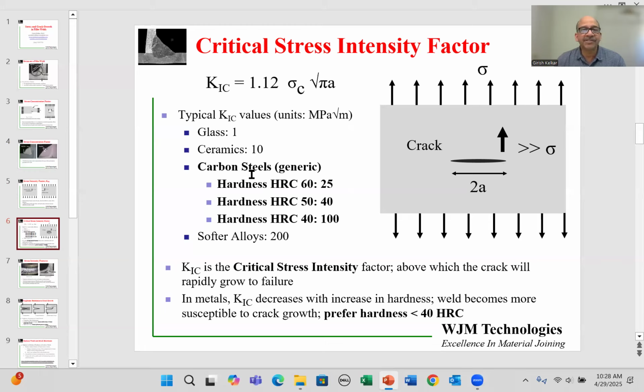Further down, carbon steels, which is our favorite material for welding most of the time: when the hardness of carbon steel is 60, which is very, very brittle, almost like a rock, the K1C value is 25. So anything with high carbon, when it goes to 60, the K1C value is fairly low. If the hardness drops to 50, the K1C value is 40. If it drops to 40 on the HRC scale, Rockwell C scale, the K1C value goes to 100. So this is an important trend to notice. As the hardness of the steel goes down, the K1C value goes up. And we want a higher K1C value because a higher K1C value means we can apply a greater amount of stress for a given crack size, and it won't lead to failure.